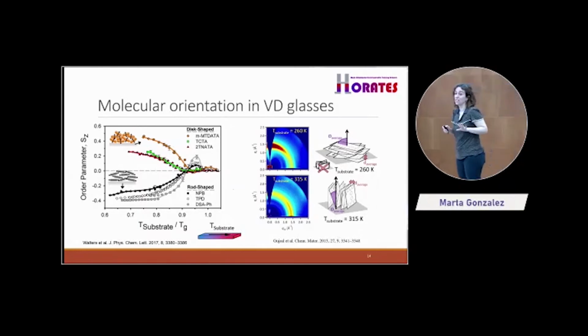More properties of these glasses, and this is quite particular. These glasses, when you vapor deposit them, depending on the deposition conditions, that means temperature and rate, they can present different orientation and molecular packing. Okay, a glass, I told you, is a disordered system. If you prepare a glass from the liquid, the molecules or the atoms, depends if it's metallic or whatever, they are completely disordered. There's no correlation, okay? It's not order at all.